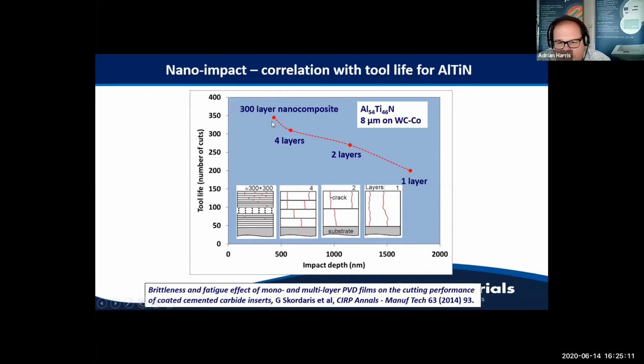And what's happening in these nano composite type coatings is that a crack can start to form. It can grow through one layer of the nano composite, and then the crack reaches the interface between one layer and the next, and that interface is sufficient to blunt the crack tip. Okay, so it actually can stop that crack from growing any further. Other cracks can grow underneath the surface, but they tend to be isolated from each other. So it takes a long time then to build up cracks that actually join together and lead to a complete